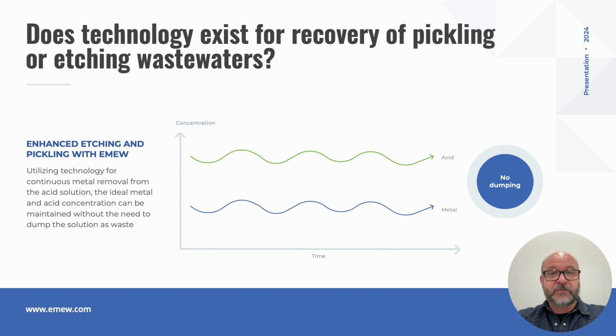Typically, utilizing this type of recovery technology can reduce the overall waste disposal volume and cost, 35 to maybe as much as 50%, in addition to reducing the acid purchases, 40 to 60%, and provide some upstream operational and production benefits. However, a complete closed loop recovery is not achievable using this type of technology in all cases because the metal fraction that is generated from these recovery systems still requires to be neutralized, converted to a solid waste, and then is disposed of.